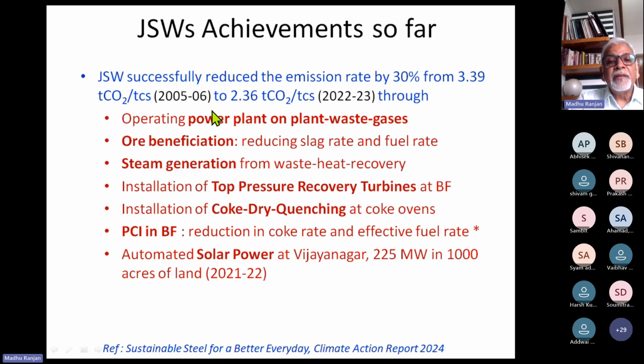So first we see what they have done to reduce from 3.39 in 2005-6 to 2.36 tons of CO2 emission rate in 22-23. So the major actions were operating power plant on plant waste gases, beneficiation of iron ore to reduce gangue and therefore reduce slag rate and fuel rate, steam generation from waste heat recovery at different levels, installation of top pressure recovery turbines at blast furnace, installation of coke dry quenching CDQ at coke ovens. We'll talk about them in a little more detail.